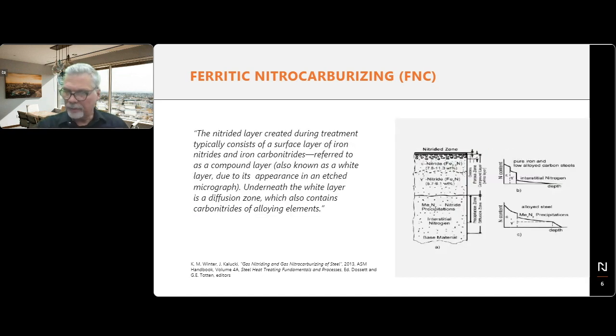One of the properties of this surface layer is to reduce corrosion and pitting corrosion. In carbon steels, the diffusion layer is not necessarily very hard, and it's not much harder than the core. The white layer contributes to most of the hardness. If you look at the two small diagrams completely to the right, on top what you see is your carbon steel, which has, as I said, very low hardness.